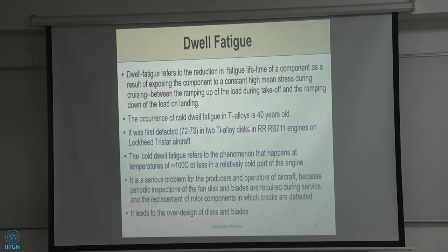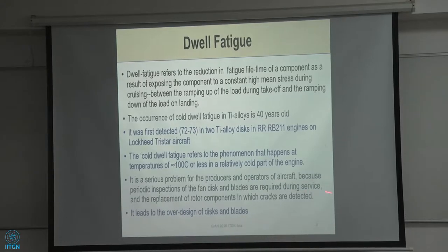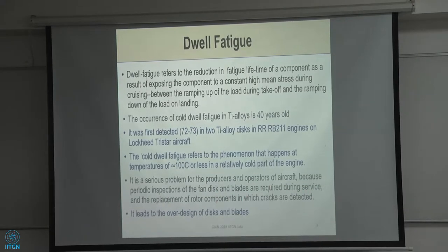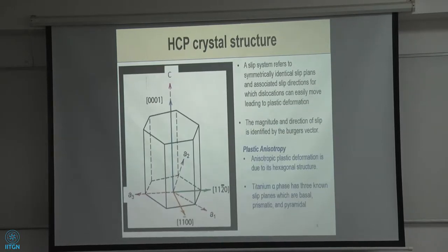I made some remarks here: what is dwell fatigue? It refers to the reduction in fatigue life. You know that there is a fatigue life by regular cycles, but when you put in that hold time, you find that the fatigue life of a component goes down, as a result of exposing the component to a constant high mean stress during cruising, between the ramping up and taking off and landing. So that dwell time that you have there is what can bring down the fatigue life, okay? And you can change that mean stress back and forth, up and down.